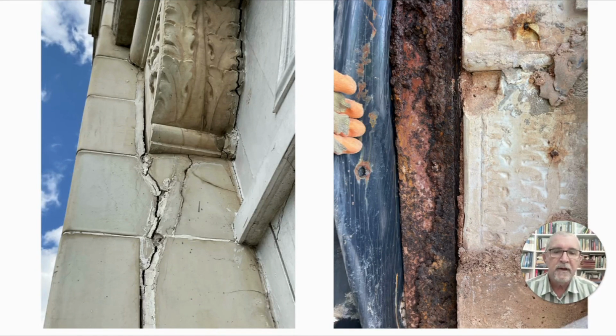This is something on these images which some younger surveyors will often refer to as Regent Street disease. That terminology, incidentally, arose from the early part of the 1900s when Regent Street was being constructed largely of metal frame buildings, which were then faced in stone and brickwork, or in this case, faience, without any adequate protection of the steelwork, which then expands and causes these vertical cracks, as you can see here.